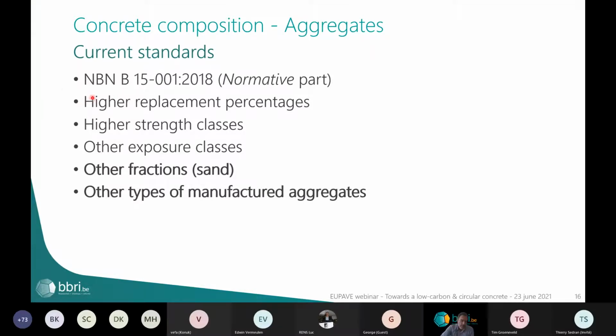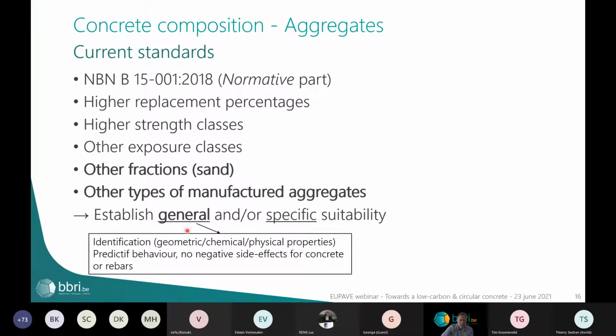The standard says that, in fact, if you want to go higher in replacement percentages, higher in the application, so the strength classes and the exposure classes, when you want to use other fractions or other types of manufactured aggregates, you can do it, but you have to establish the general and/or specific suitability. For some of the aggregates already described in the standard, the general suitability does not have to be established, but only the specific suitability. And with the general suitability, in fact,